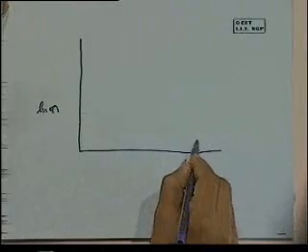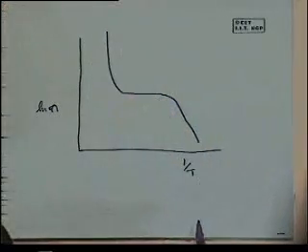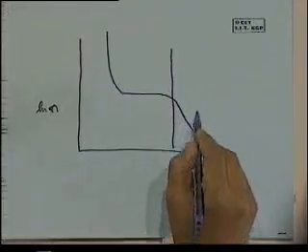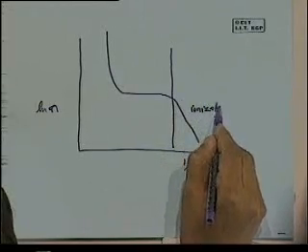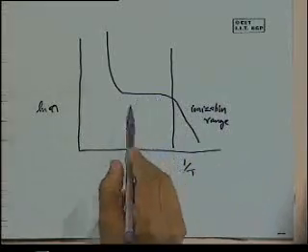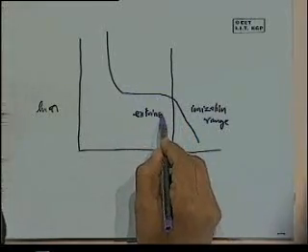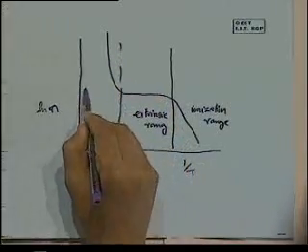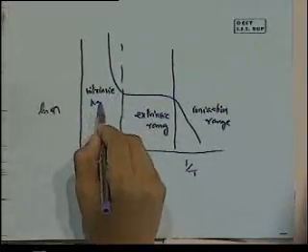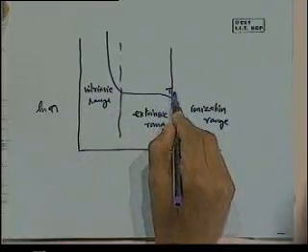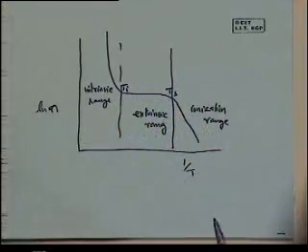Taking up from where we left off yesterday, we had looked at the temperature dependence of carrier concentration. If we plot the carrier concentration versus 1/T, we see a behavior with three regimes: at lower temperatures, the ionization range; then an area of saturation, also referred to as the extrinsic range; and then the intrinsic range. Two temperatures TS and TI were identified, related to the start of saturation and start of intrinsic behavior.